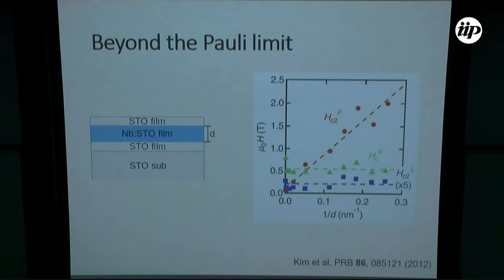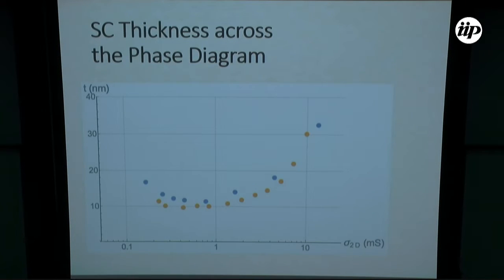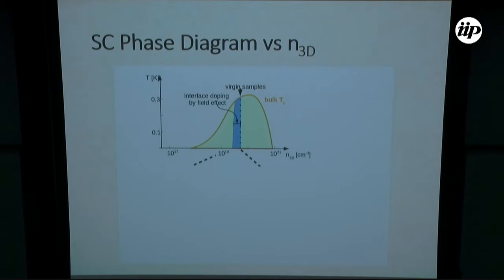So based on this experimental fact, we analyzed our curves in the same way, using the same relation between the critical field and thickness, and so we extract across the phase diagram the effective thickness of the superconducting layer. And this is what we observe. We observe a large region in the underdoped and optimally doped regime where the thickness remains constant between 10 and 15 nanometers. But as we move into the accumulation state, we see that the thickness of the superconducting gas tends to diverge. So actually the gas tends to deconfine even more into the substrate, reaching a thickness of 30 nanometers. Now with this information, we can go back to our phase diagram and compare better the properties of the interface with those of the bulk. We had previously just a sketch like that.